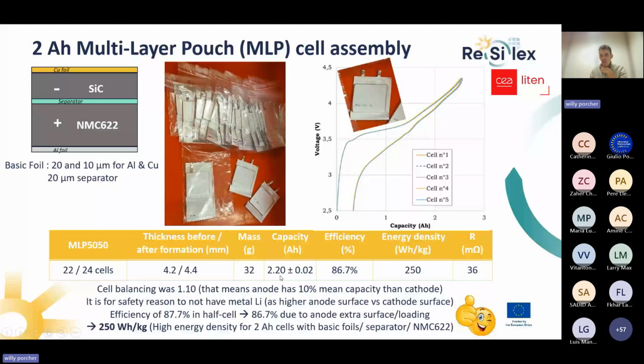You have here the voltage behavior of 5 cells, which is superimposed. Efficiency was 86.7% at the first cycles. So it's slightly lower compared to the half cell. It's due to extra surface that you need to put in the cells to avoid lithium metal, to avoid a safety issue. And at the end, we have a cell with an energy density of 250 watt-hour per kg, which is very, very high, especially if you consider the basic foils and separator that we integrate. So a really high energy demonstration at cell level of this silicon carbon composite.